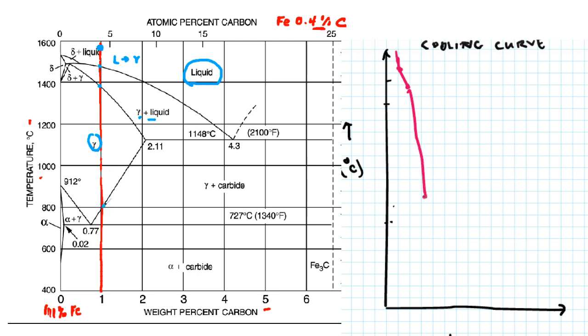At this temperature we cross the boundary into the gamma plus carbide phase region. So we know we started with gamma, and then as we enter into this phase region we're getting a transformation like this: gamma is forming Fe3C. Not entirely, but here's the carbide that's this line here, just as a reminder. It's 25 atomic percent carbon. So as you enter this region you get more carbide that forms.